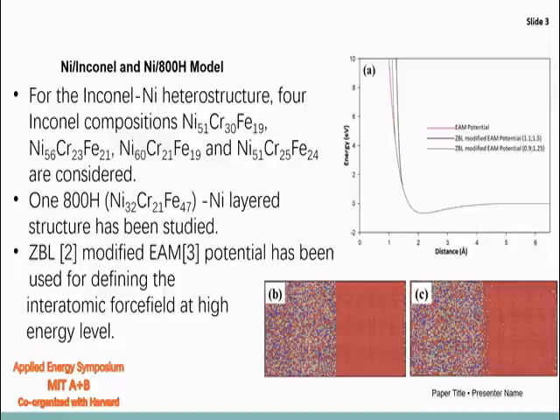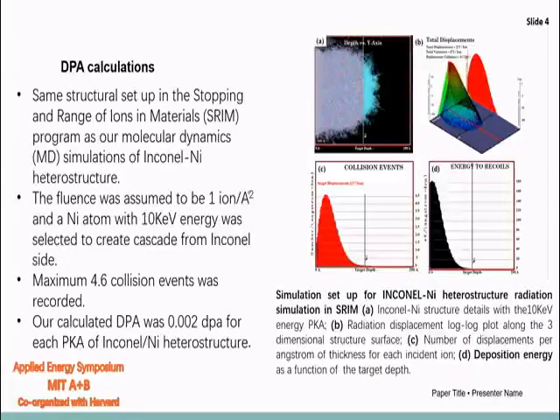To get to this radiation dose level, we have to introduce 250 primary knock-on atoms into a structure. So we have used the SRIM calculation to calculate the value of DPA for each primary knock-on atom in the nickel Inconel heterostructure. We have set up the SRIM simulation with the same setup that we have used in the MD, and with the same structural conditions that we have in our molecular dynamics simulation. After the calculation, we got a DPA level of 0.002 DPA for each primary knock-on atom in our structure.